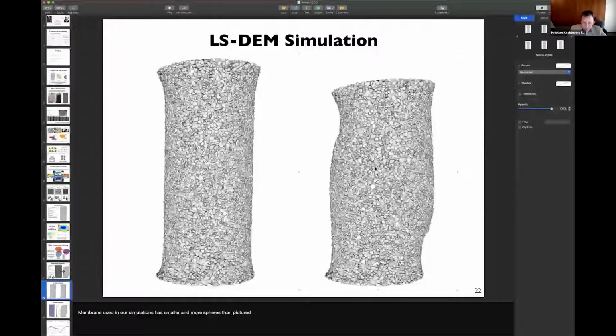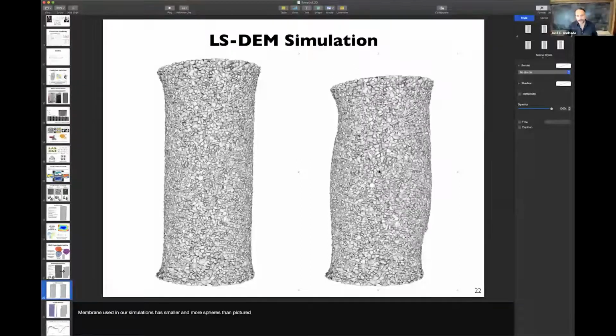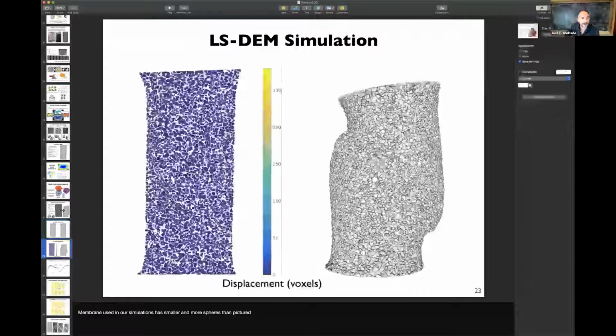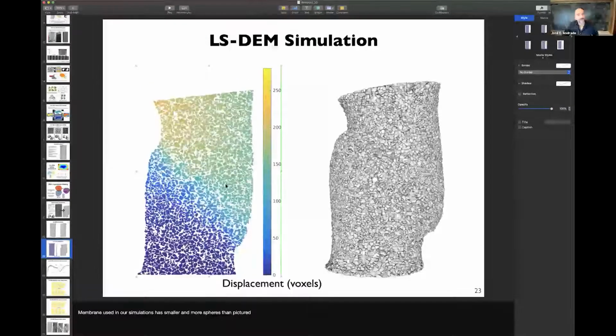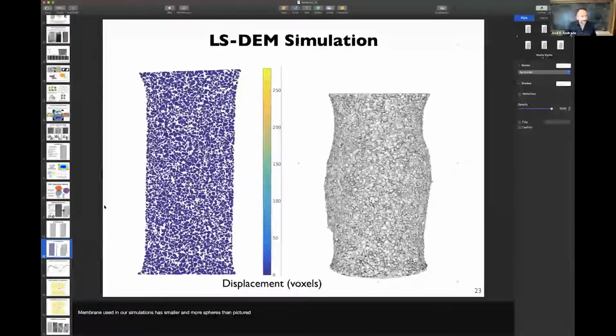All right. So here on the right, you can see the ultimate deformation of the sample, right? How from the vertical deformation of the platen, notice that the platen is allowed to tilt, you get this beautiful deformation pattern. You see a shear band actually that forms and so on. So you're starting to get very realistic deformation patterns that seem to match what you expect in reality. Here is starting to get more quantitative. This is a slice of that same experiment showing the vertical displacements. And here it's just a rotated image of the deformed sample.